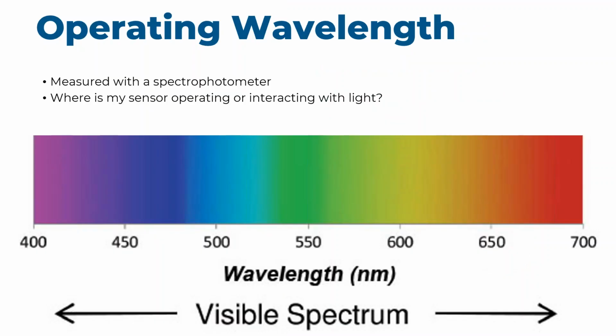So I used a few words there kind of talking about reflectance, transmission. These are all probably review for most people involved, but operating wavelength is basically measured with a spectrophotometer, and it's really asking, where is my sensor operating? How is it interacting with light? If I'm working on a visible spectrum application, 400 to 700, what have you, take 50 nanometers left, 50 nanometers right. If I have a near IR requirement, I don't really need to specify too much in the visible if my sensor's telling me I don't need to. So understanding how your sensor or how your application is interacting with which specific spectrum is extremely important. That helps us decide on what materials we're going to use, what thicknesses we're going to need to deposit. A vast array of other aspects go into deciding what coating we're going to use to meet your specification. Operating wavelength is probably the key in almost all of those.